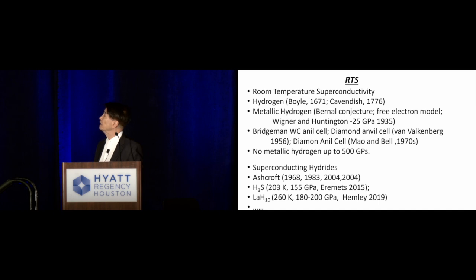Then the second thing that happened is, what about superconducting hydrides? Because pure hydrogen, you squeeze it, even to that high pressure, it's not even metallic, let alone superconducting. So people thought about different methods. Actually, the person who first proposed metallic hydrogen and also metallic hydride superconductivity was Neil Ashcroft at Cornell, in 1968, after BCS theory was proposed in 1957. He said, well, you look at the formula, you can get it. It should be superconducting. Of course, it did not happen.